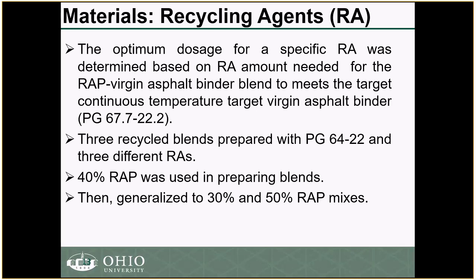So for the recycling agent, to determine the optimum dosage, we did binder testing. We blended the RAP binder with the virgin asphalt binder in the same proportions as in the mixture, and used different dosages of the recycling agent. Based on that we determined the optimum dosage that results in a continuous performance grade for the RAP and virgin asphalt binder blend that meets the target virgin asphalt binder continuous grade, which in this case was 67.7 minus 22.2.